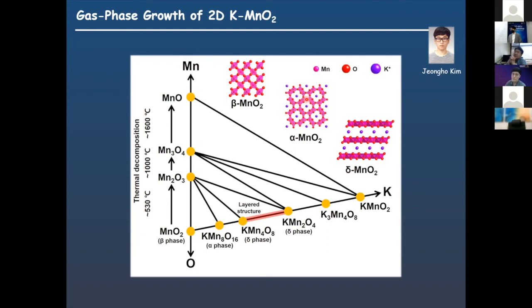The mechanism of forming the monolayer is that the lateral direction is quite chemically reactive, while the top basal plane is chemically unreactive. So through the chemical reaction between the existing flake and the incoming element, the monolayer material can be grown. But in the MBE case, it's introducing the element directly, so it's more difficult to control the number of layers.